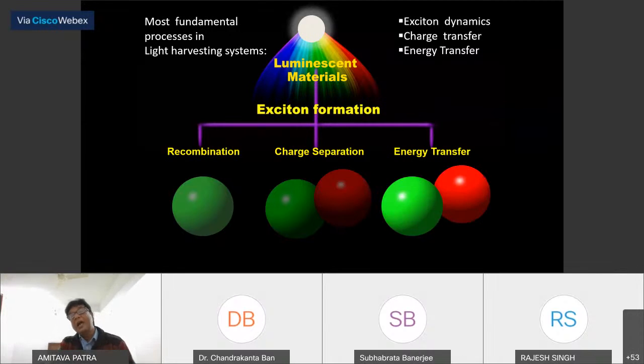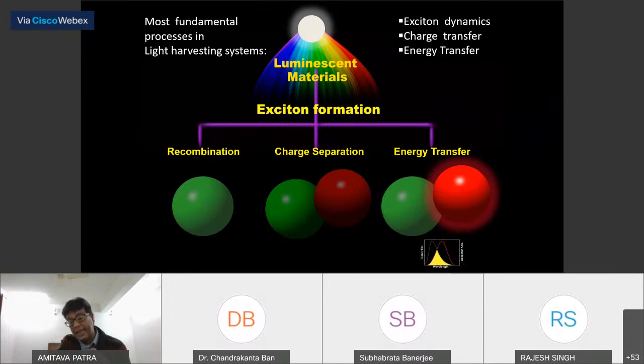How the electron first goes from one state to another state, what the kinetics is, that is very important. And finally, the energy transfer process is another important thing, because in your M.Sc course, maybe you will go for energy transfer by the FRET process, Förster resonance energy transfer, where there is a donor molecule and an acceptor molecule. If you excite the donor molecule, that energy can transfer to the acceptor molecule. There should be overlap between the emission band of the donor and the absorption band of the acceptor.